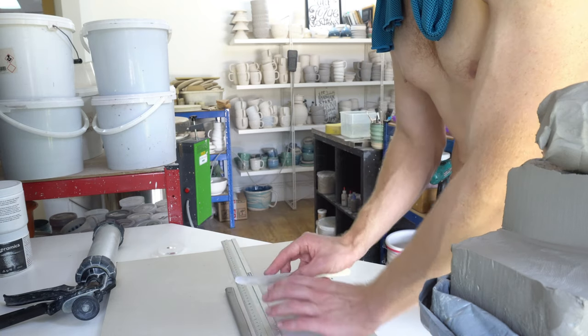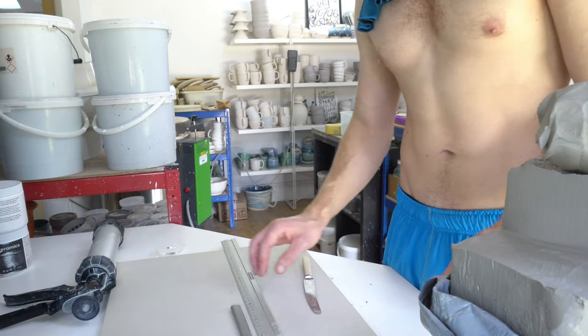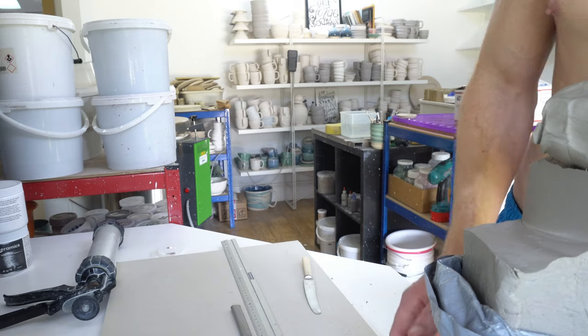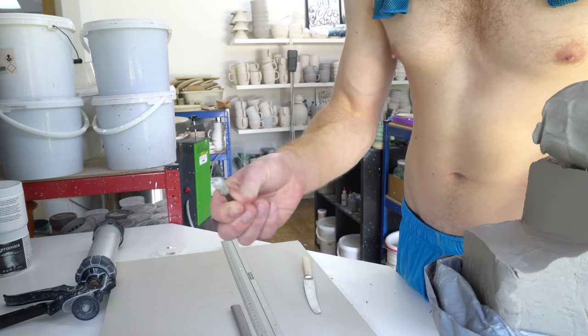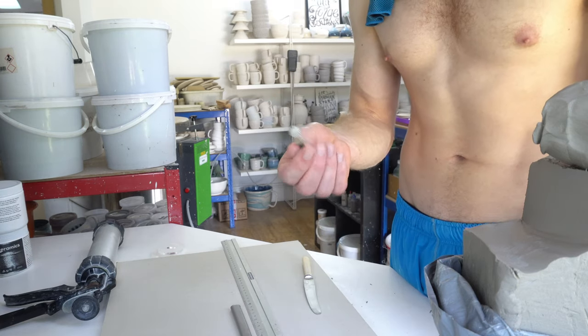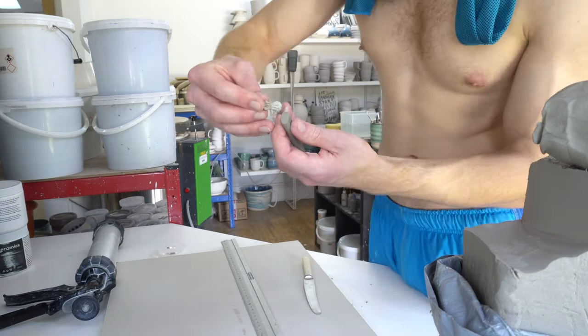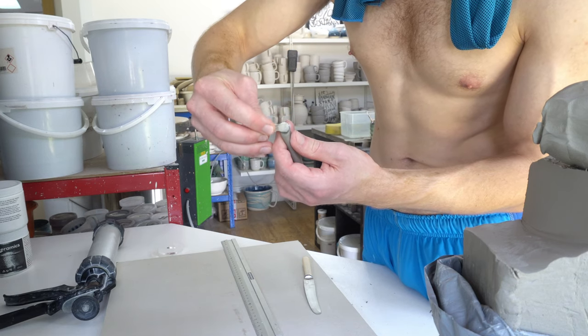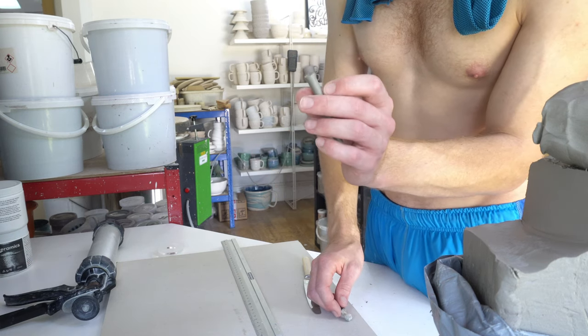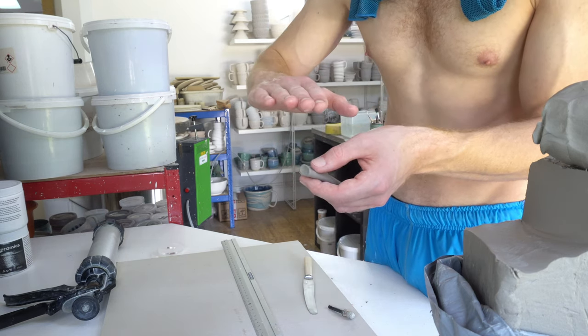My small handles I do to 9.5 centimetres, and this is with the smallest of my standard dies, which is 8 by 16 millimetres. And then what I do is I take a rotary grinding bit. It doesn't have to be one of these, but this is what I stamp the peacock eye design with as well. They're just a handy tool in terms of texturing and things. And if I roll it across the end, what you'll see is that it has flared it and given some texture. So now when that sticks, it'll stick really well, and it'll also create a join.